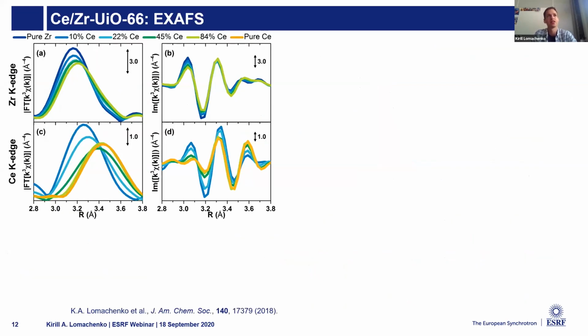So what was done is a measurement at cerium K-edge and zirconium K-edge for a series of materials with different cerium content from 10% to 84%, and also the pure compounds.